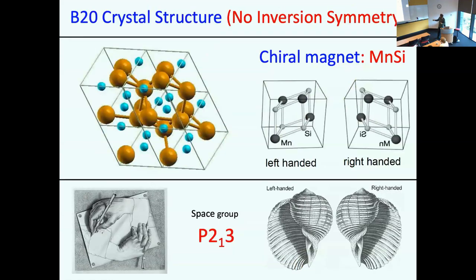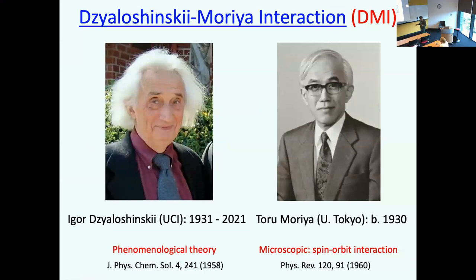The only thing you need to know is that this crystal structure lacks centrosymmetry. That means if I put a mirror plane, I cannot overlap them. This is very important because breaking inversion symmetry especially leads to some properties which will become clear in a moment, this handedness, okay? This basically means you have what is known as the Dzyaloshinskii-Moriya interaction, DMI, in the magnetic system. So Igor Dzyaloshinskii was a student of Lev Landau, and he wrote this paper way back, just phenomenologically in the spirit of Landau, that you have a symmetric interaction in spin, Si dot Sj, but there must be an antisymmetric interaction, Si cross Sj. So he wrote that